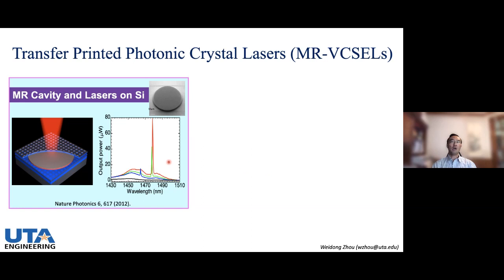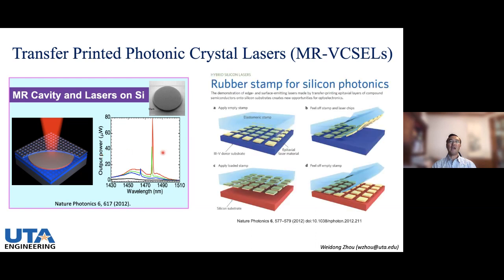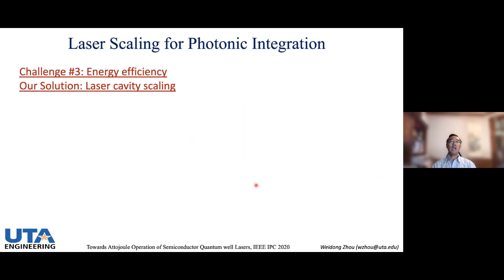That's what I achieved: realizing the laser on a silicon substrate with a silicon photonic crystal reflector and a transfer printing process. In fact, one review called it the rubber stamp for silicon photonics. Basically, you pick up the material using PDMS and print it onto a different material. Now this field has picked up quite a lot in Europe, in Asia, and in the US as well. So what do we work on now?